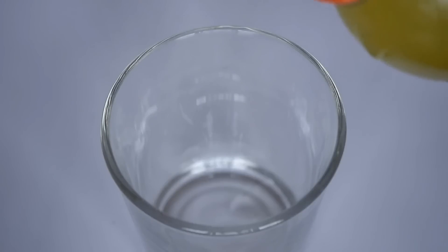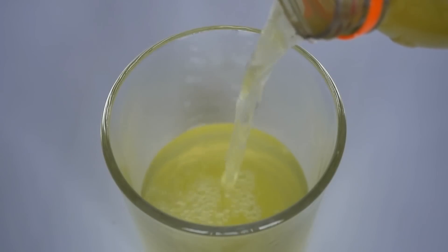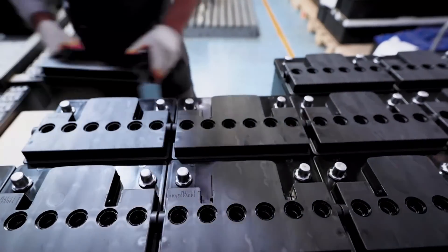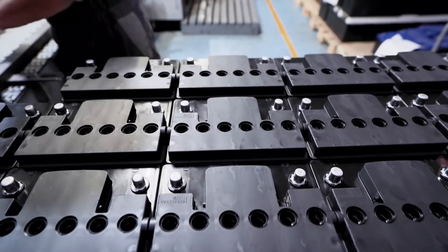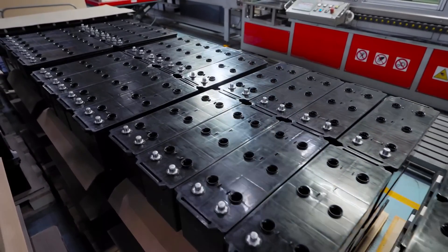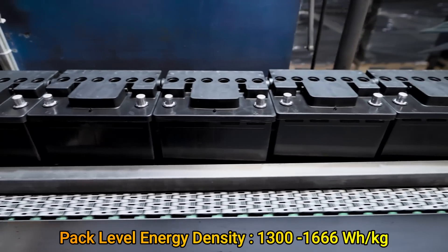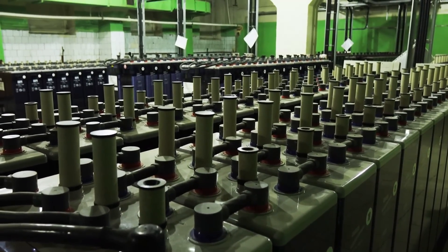The electrolytes are no longer toxic. Furthermore, these new non-toxic electrolytes do not require aluminium of very high purity, and by using the right aluminium alloys, the coulomb efficiency has been increased. As for non-rechargeability, if swappable battery packs can be made — where used packs are swapped with fresh ones — this problem is somewhat addressed. Aircraft fly port to port and fresh batteries can be replaced with ease at these stations. Using aluminium-air batteries, a pack-level energy density of 1,300 to 1,666 watt-hour per kilogram is possible, and the pack is safe and does not even require a cooling system.